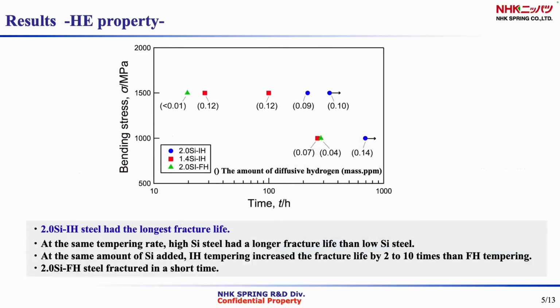I will move on to the result. This is the result of the hydrogen embrittlement property of each specimen. It was found that 2 silicon IH steel has the longest fracture life. At the same tempering rate, high silicon steel has a longer fracture life than low silicon steel. At the same amount of silicon added, IH tempering increased the fracture life by 2 to 10 times compared to FH tempering. And 2 silicon FH steel fractured in a short time. Therefore, it was expected that there would be a large difference in microstructure compared to FH tempered steels.